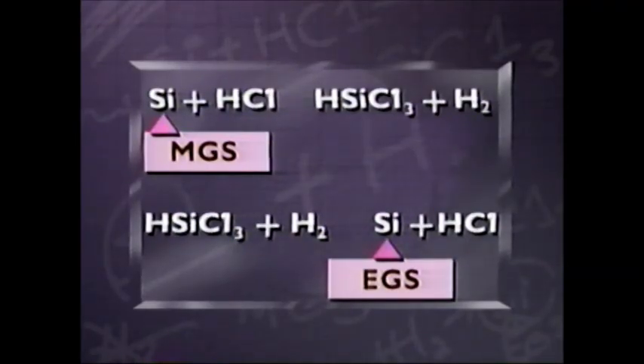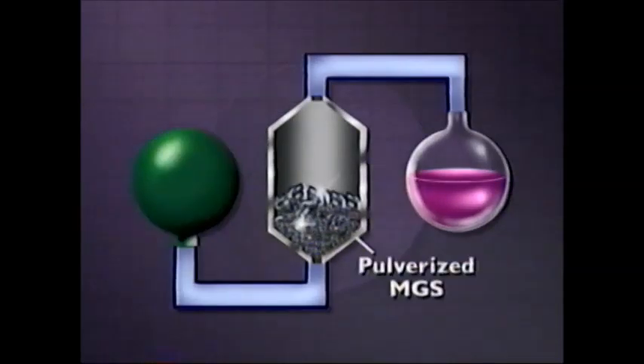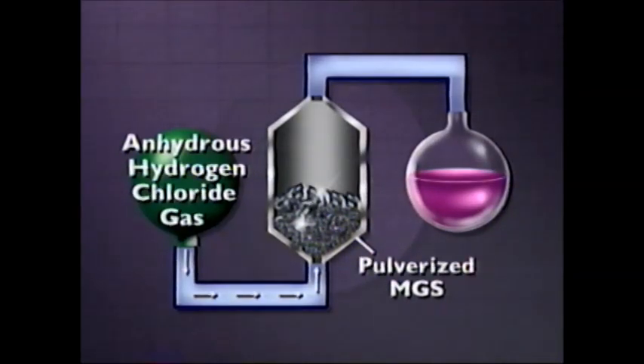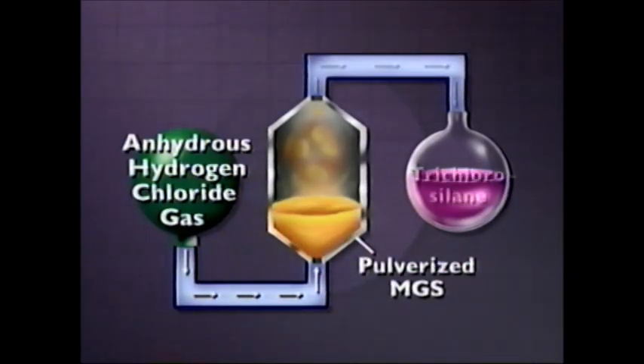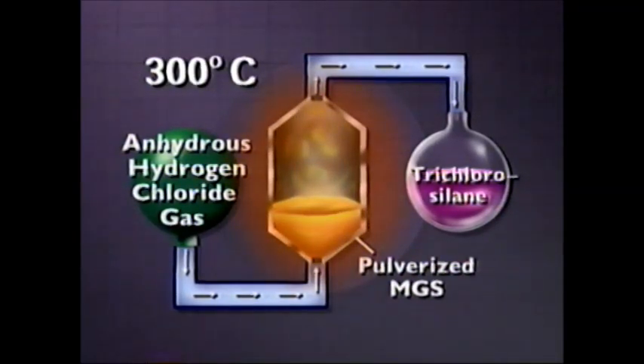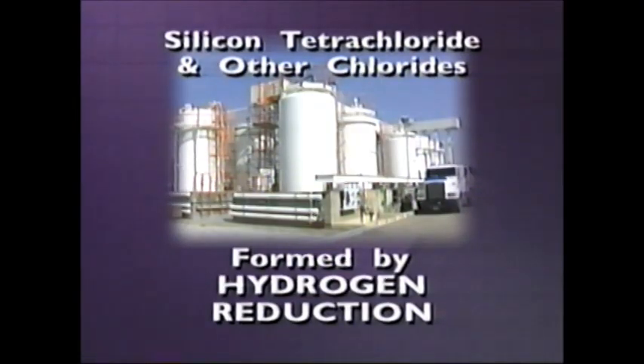To transform MGS into high purity EGS, the MGS is pulverized and made to react with anhydrous hydrogen chloride gas to form trichlorosilane. This process takes place in a fluidized bed at 300 degrees centigrade. Silicon tetrachloride and the chlorides of the impurities are formed by a method known as hydrogen reduction.